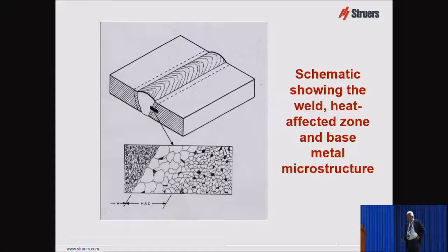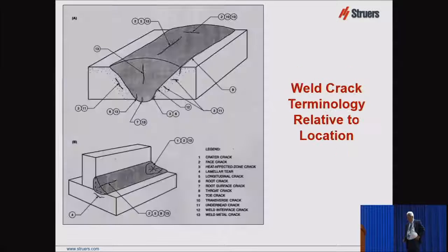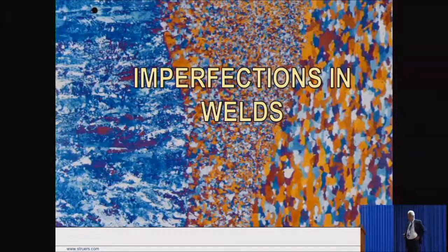There we go. Here's our weld bead and the weld direction, and we're going to look at this region right in here. This is the weld metal, the fusion line, the heat affected zone, and the base metal. And these are important parameters. There is a great deal of terminology that's used with respect to defects in welds, and you can see some of them will have multiple names, like face crack and longitudinal crack and weld metal crack and so forth. But it's important that when you're discussing failures of welds in a report, or if you're doing a failure study, maybe a court case, it's important that you use the right terminology. Now, I'm going to look at a few imperfections in welds.